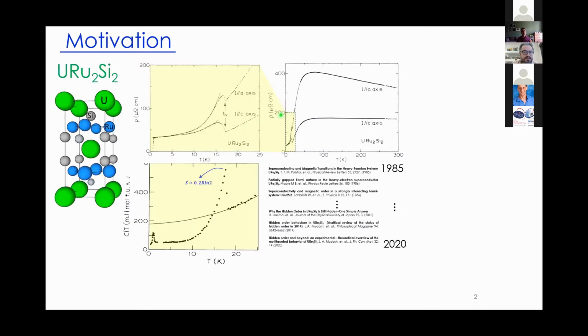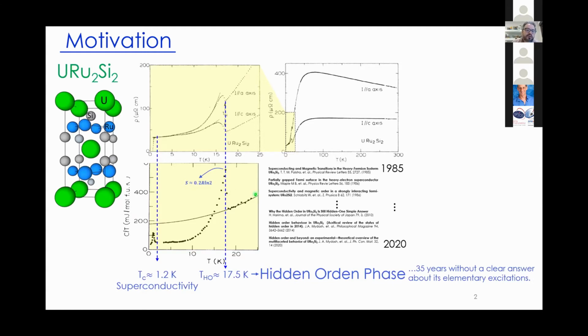The history of uranium-ruthenium-2 silicon-2 begins in 1985 with the reports of two transitions by resistivity and specific heat measurements. One transition at 1.2 Kelvin was identified and confirmed as a superconducting phase, and the other below 17.5 Kelvin, in which there is a large entropy change, was also reported. This phase is known as a hidden order phase because the microscopic origin is not clear.